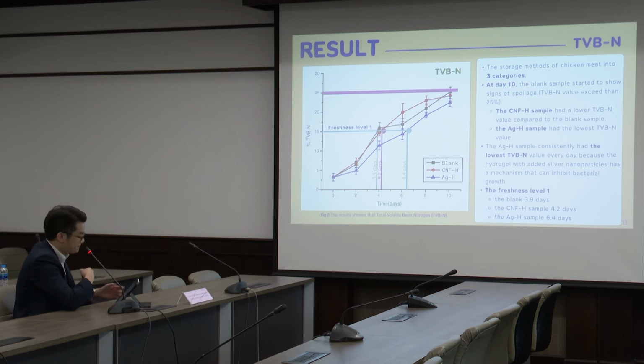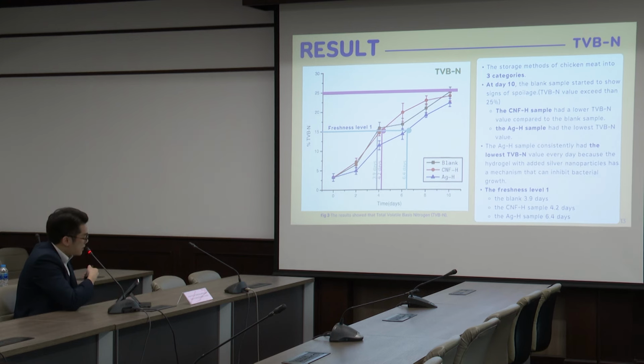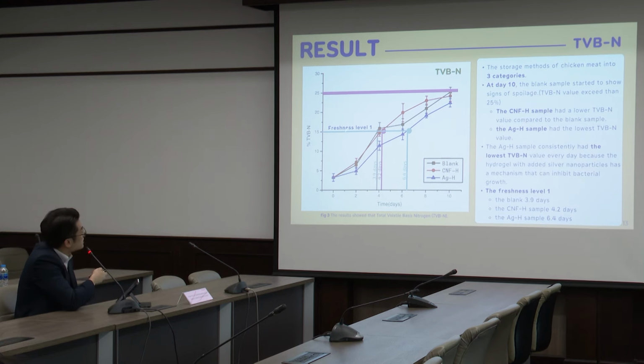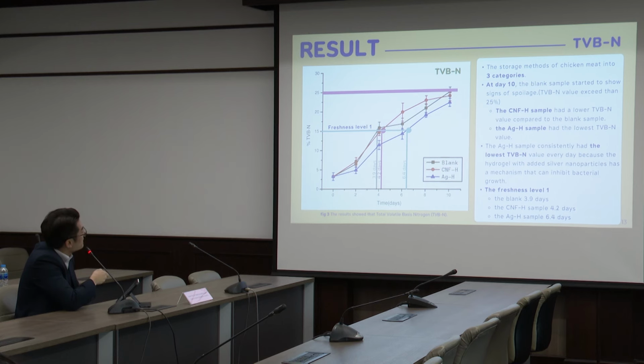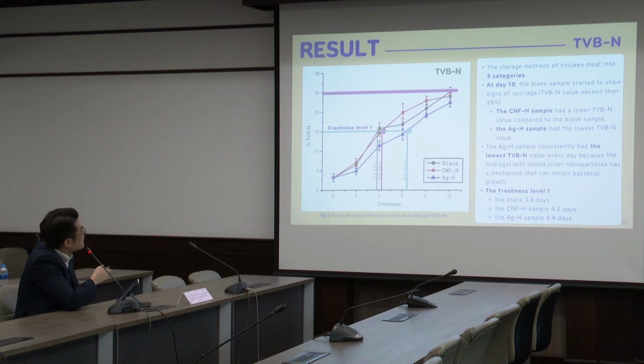0.015 phr. If you see in this graph, at all storage times, we observe an increase in TVBN, and at day 10, the blank sample starts to show signs of spoilage, as the TVBN value exceeds 25. Moreover, we found that the AGH consistently had the lowest TVBN every day, as you can see in this blue line. This is because the hydrogel has silver nanoparticles that can inhibit bacteria growth.